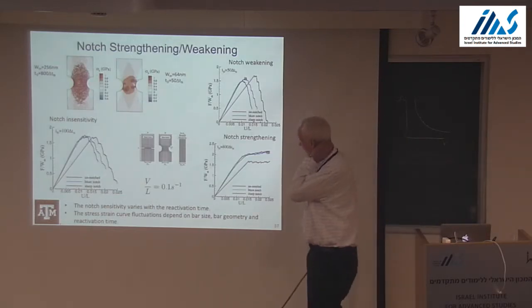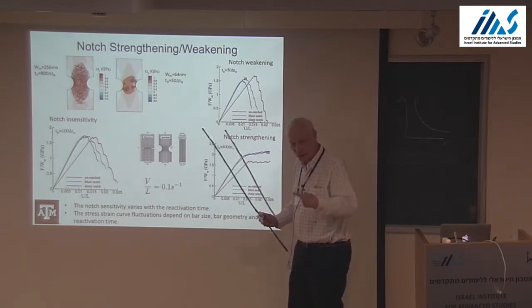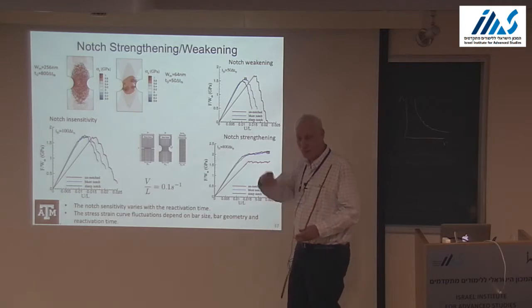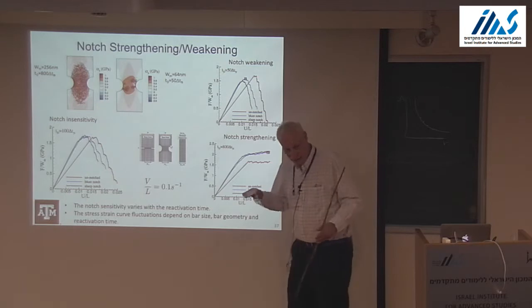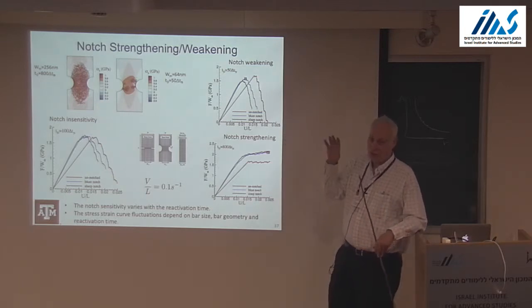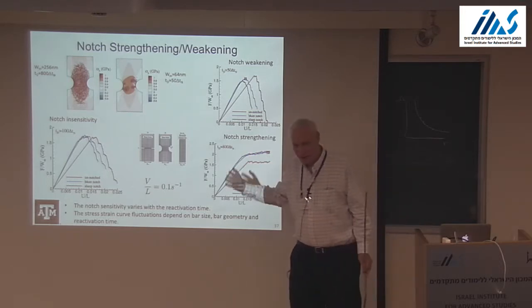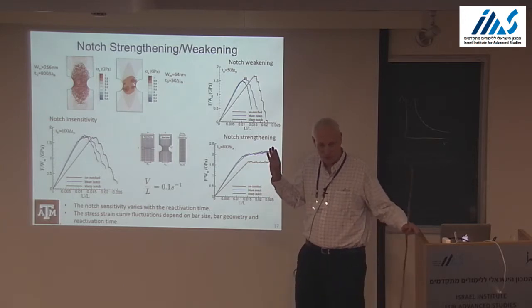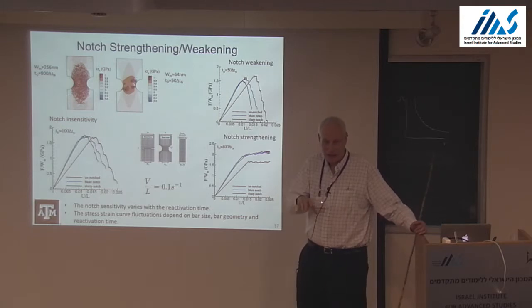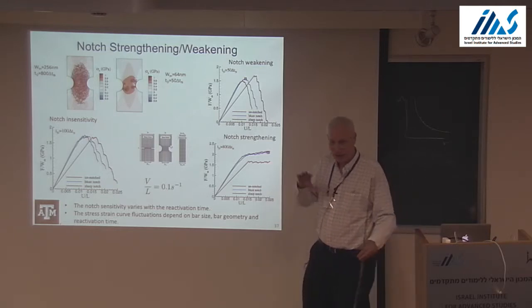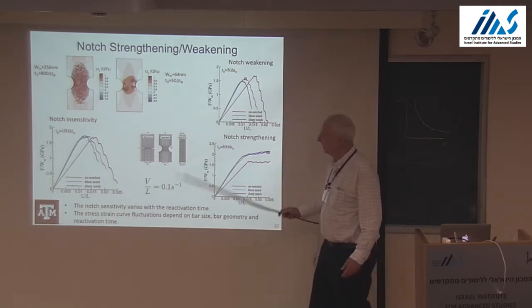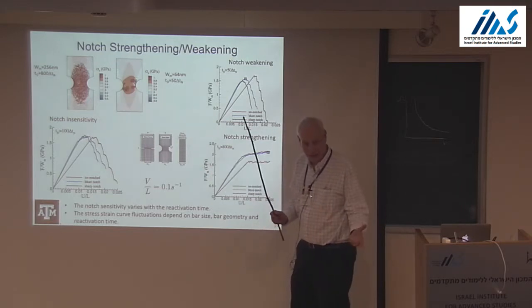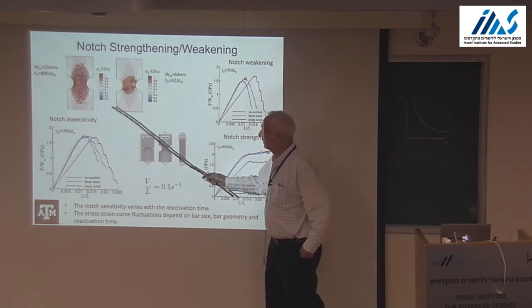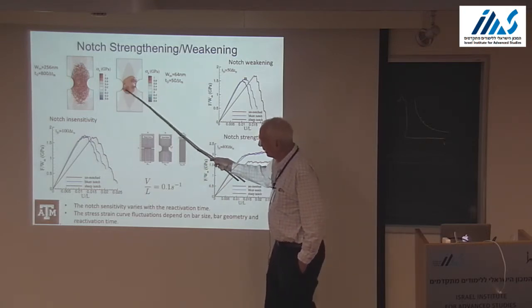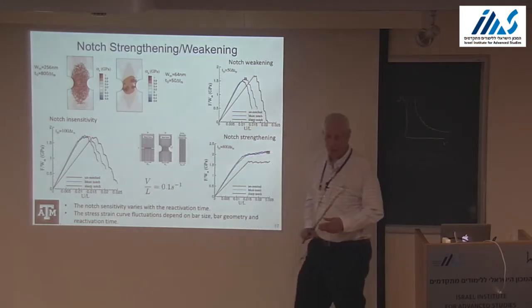What comes out from our very simple calculations is that it depends on this reactivation time. So you can get notch weakening if these reactivate quickly, which gives more brittle type behavior. With more time between these reactivation events, you get more ductile type behavior. This is not at all accurate. I wouldn't claim that this represents real materials, but what this suggests to me is, again, the time scale for making more strain, whether it's new STZs or reactivating old ones, is key for understanding how these things respond to gradients. And what that affects is how the hydrostatic stress develops in the region between the notches. Here you get more localized hydrostatic stress. Here you get more spread out hydrostatic stress.